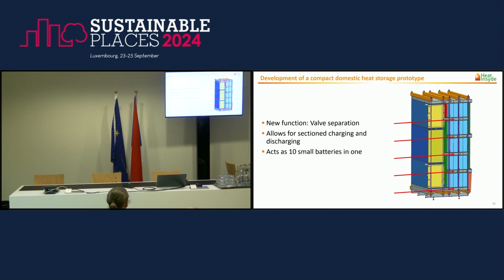Secondly, we have introduced valve separation. Henk already told you that one of the biggest problems with this material is the cycling. And if we cycle the material a lot of times, the pressure drop increases and the efficiency goes down. One way to solve this, at least on a prototype level, is to not discharge all of your salt at once. We have separated our TCM reactor basically into 10 small reactors, giving us 10 small batteries,